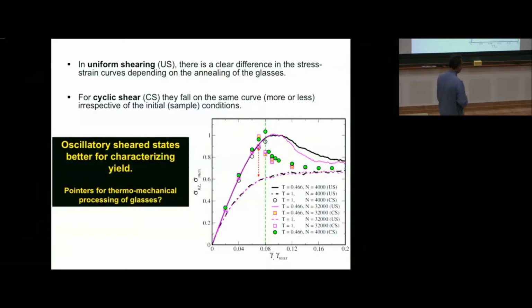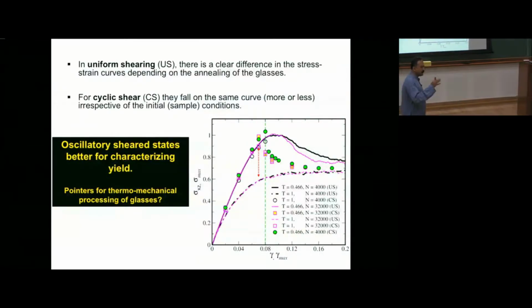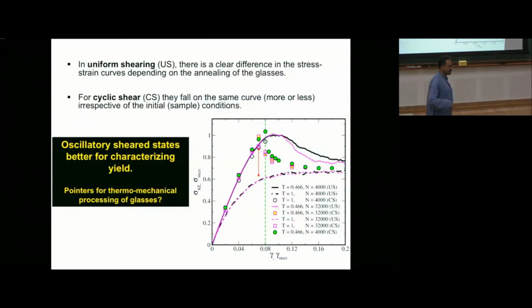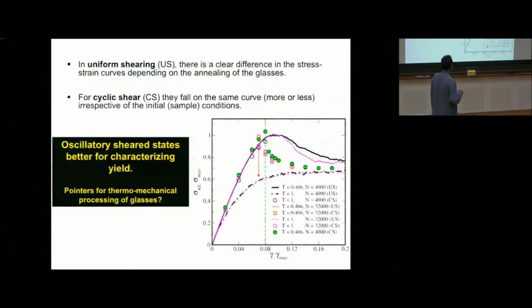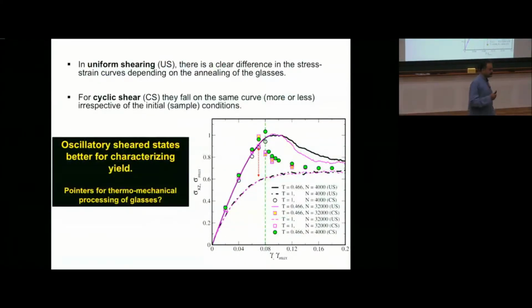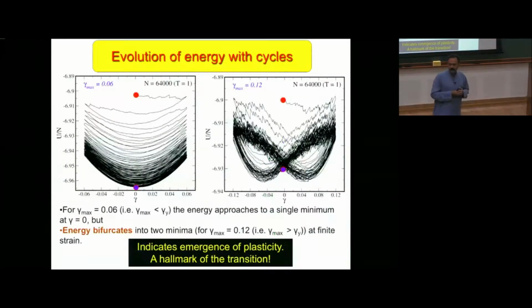So one thing that is related to what you asked is, if I started with this poorly annealed glass, by the time I'm done with my cycling till I reach a steady state, my stresses have gone up to here, right? So you've actually work hardened the glasses, right? But work hardening is, in fact, also a known phenomenon in crystalline solids, but let me not spend more time on it. The long and short of it is, we have a way of identifying a sharply defined yielding transition.